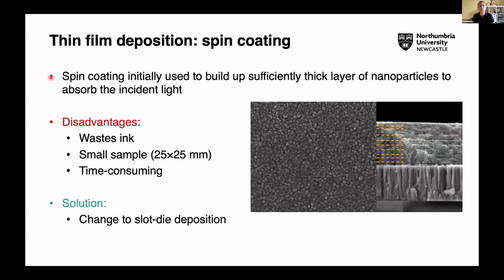What we find is using this spin coating deposition technique, it works rather well. We can make these kind of really compact nanocrystalline nanoparticle layers, and they can absorb the light. And we can build up these layers here in the right diagram by just repeated spin coating, and you can see the layers here indicated like that.